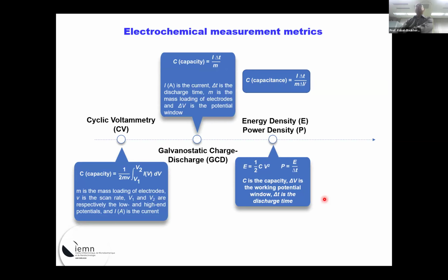So just to give you some metrics, I think you do know about what we're going to look at. That's what you get from cyclic voltammetry, the capacity or capacitance. Indeed, capacitance when you have an EDLC, but when you have a Faradaic type or intercalation or pseudocapacitor, you talk about capacity. So that's typically what you look at when you prepare electrodes for a supercapacitor. You look at these metrics, but also you look at the stability, and you want as well to reach a high energy density and high power density with something which is very, very stable.